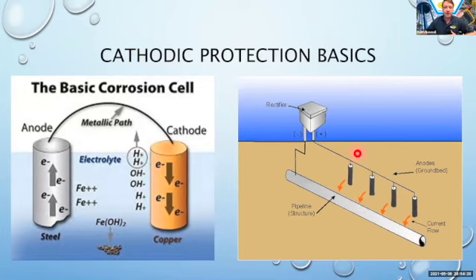We energize it with this rectifier, which basically takes your AC voltage and converts it to a DC voltage, and that DC voltage is what energizes our anodes in this system. And then in turn it produces conventional current flow from the anode to our cathode, to our piping, which in turn protects that piping from corrosion.